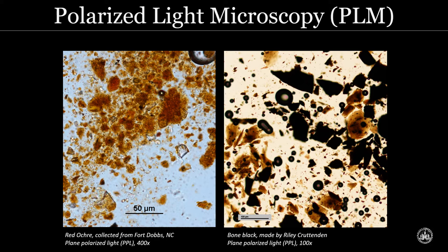Polarizing light microscopy, or PLM, is another technique I use to identify pigment particles based on their optical and morphological properties in transmitted plane and cross-polarized light. To do this, I collect a few grains of the pigment on the tip of a scalpel or a very fine tungsten needle, and I disperse them onto a glass slide. These samples are extremely small, and often I can't even see them with my naked eye when I'm preparing them.